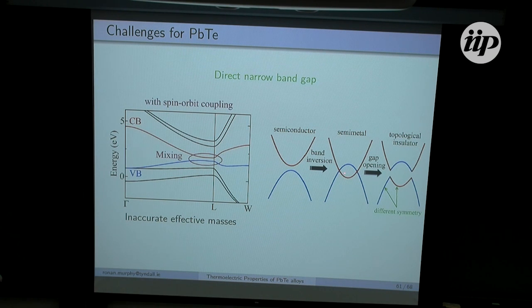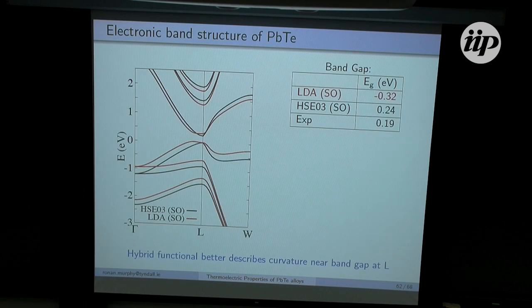What happens then is a slight gap does open up, but because of the crossover and the negative band gap, the character of the states, say here and here, is different. So if you try to calculate the effective masses from this band structure, they're going to be very poor. To get around that, we have to go beyond this basic approximation and start looking into something like a hybrid functional.